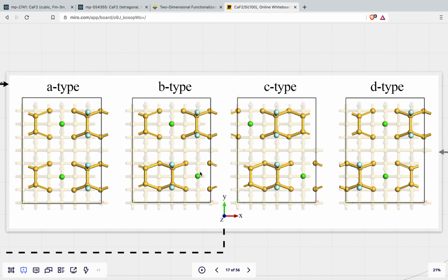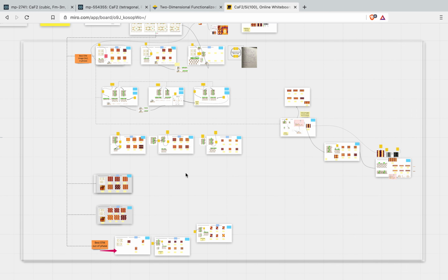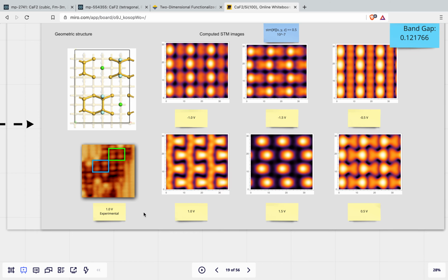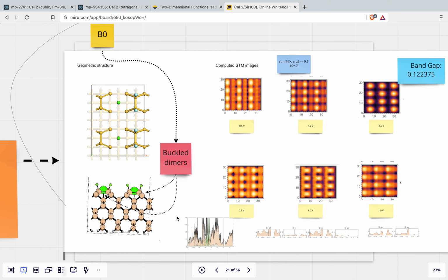For the different possible wetting layer formations, and returning again to our tree of possibilities, we used the simulated STM images as criteria for comparing against the experiment. We can observe that it was not just a matter of inverting the order to get an adequate pattern. For example, in here we can see that this one does not get close to the experimental data, even being in the same voltage configuration of the STM. Neither did this option. So after a lot of trials, the best configuration for the in-phase structure was this one.